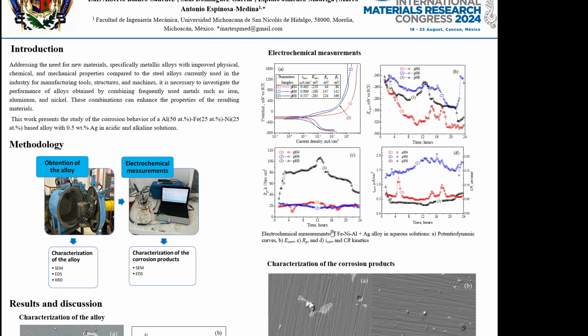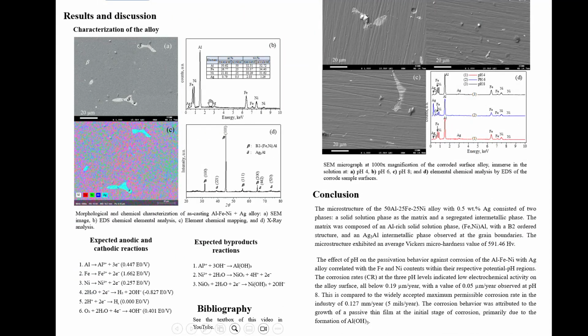The expected anodic and cathodic reactions are the oxidation of aluminum, iron, and nickel from metallic state, the reduction of water molecules producing molecular hydrogen, and the reduction of oxygen with water producing hydroxide anions. In addition, the expected reactions of the corrosion byproducts are the formation of aluminum hydroxide, nickel oxide, nickel hydroxide, and of course, iron oxide.